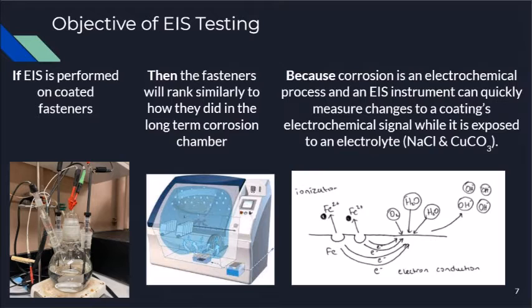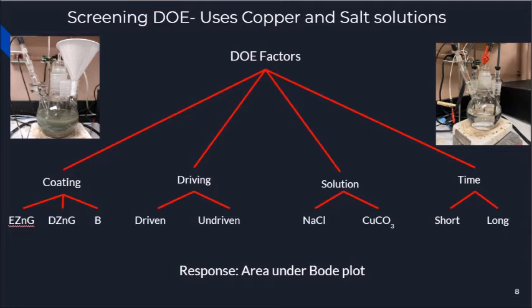This is our hypothesis for this project. It was, if EIS is performed on coated fasteners, then the fasteners will rank similarly to how they did in the long-term corrosion chamber, because corrosion is an electrochemical process and an EIS measurement can quickly measure changes to a coating's electrochemical signal while it is exposed to an electrolyte. And then this is our overall DOE that we use to assess the most important factors among coating, driving, solution,